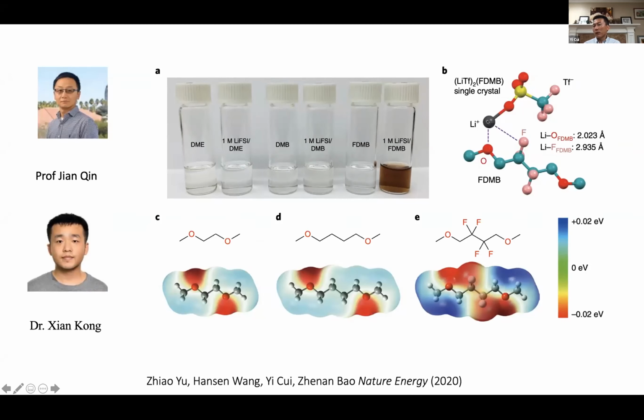The reason is, through simulation, we found out lithium coordinates with the anion and with FDMB through fluorine and oxygen, forming this ring molecule. It's a ring molecule right there, you see. And this ring molecule somehow creates a certain degree of electron resonance structure, and the absorption gives you this color. It's very, very interesting. This is a complete surprise, that we wouldn't expect this to take place. So this is due to this very interesting solvation structure. So we are going deeper right now in understanding this.